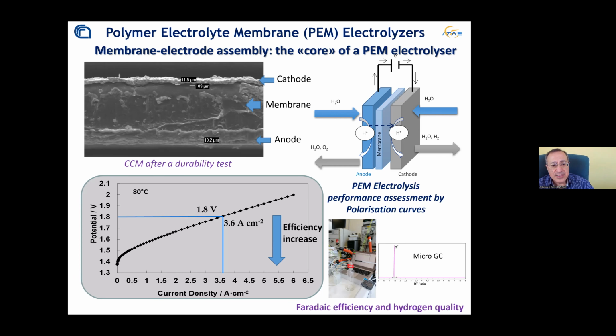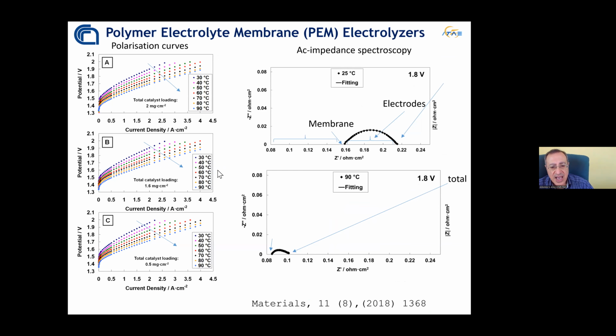Now let's move to the next slide, where I can show you two aspects. First, on the left, you can see several polarization curves at different temperatures and different catalyst loadings. You can see that the efficiency, indicated by the arrow, increases by increasing the catalyst loading. But since we use precious metals, we need to achieve a compromise. The efficiency is also increased by increasing the operating temperature.